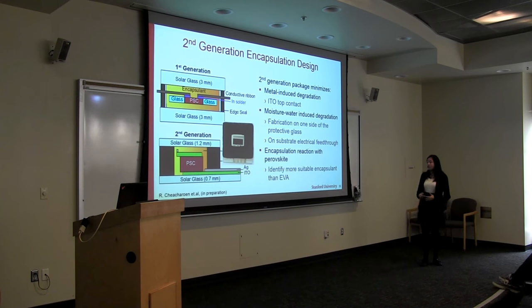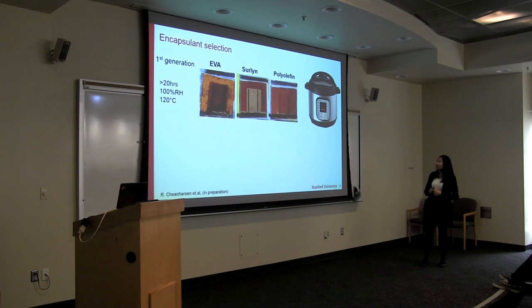Third, we need to select the perovskite with a more suitable encapsulant so that it doesn't react like EVA. So how do we actually select the encapsulant? I use a pressure cooker, which a lot of solar companies use, with the condition of 100% relative humidity and 120 degrees Celsius, which is to speed up everything that would cause the solar cell to degrade. And I compare the solar cell in three different encapsulants.